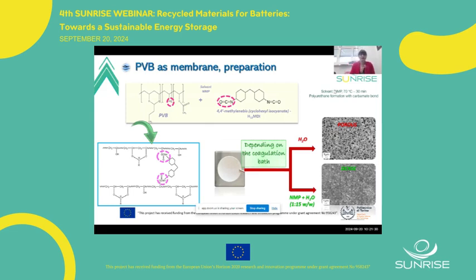And now the second part, we also used PVB as a membrane. In this case, we mix the PVB with NMP, add some isocyanate in a very low amount, and then let the solution stir to obtain a very uniform solution.